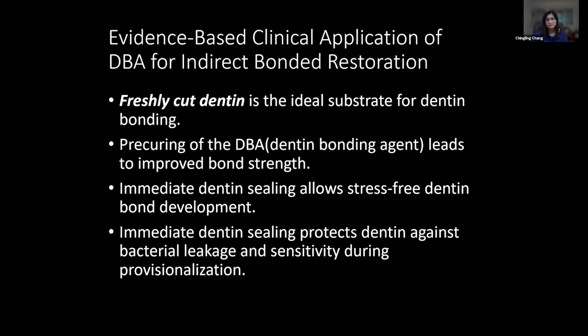After we have the dentin freshly cut, it's very ideal for us to apply dentin bonding. When we cure the dentin bonding agent, we actually improve the bond strength to the highest. And after immediate dentin sealing, we allow a stress-free dentin bond development. We don't need to worry when we apply the bonding agent when we deliver the porcelain, which might immediately create more stress on the tooth and restoration. And also with immediate dentin sealing, we protect the dentin against bacterial and micro leakage. We can also reduce the sensitivity during the provisionalization and before we deliver the final restoration.